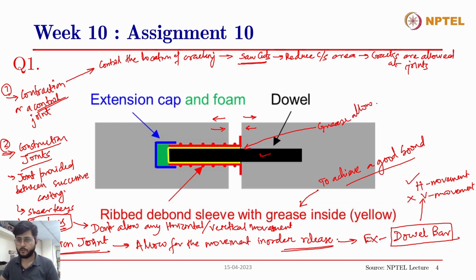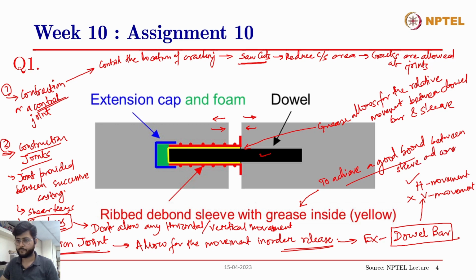grease allows for the relative movement between dowel bar and sleeve, and this provides a good bond between sleeve and concrete, right? So the grease allows for a good relative movement, so that the dowel can allow for the horizontal movement to occur. During expansion, the concrete will come closer. During contraction, the concrete will go further apart, and the grease will act as a lubricant for that purpose. But again, we want the grease to be intact in that place. It doesn't leach out into the concrete. It doesn't flow out, so that it will provide a good lubrication,